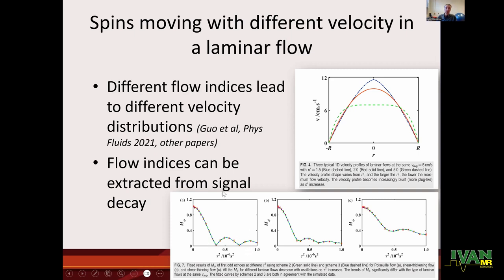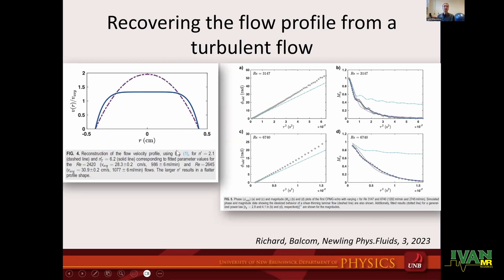These three plots at the bottom show how your magnetization changes with the echo time for three types of fluids: Newtonian fluid, shear thickening fluid, and shear thinning fluid. The same approach can be applied to, for example, turbulent flow. Turbulent flows are characterized by plug-like profiles, so again you have a different distribution of velocities inside the pipe. And again, you can observe the transition from laminar flow to turbulent flow with this approach. You can extract information on exactly what the velocity profile in your pipe is.